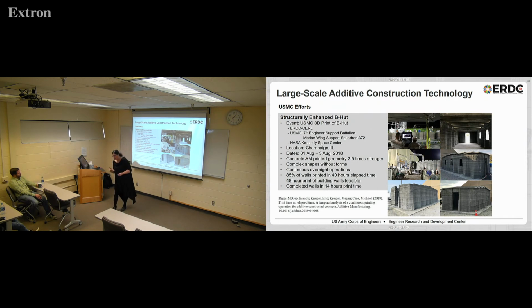And so if you feel about 6 layers down, it feels very firm. It feels like the concrete's already gone through some of its initial set. So we don't have to worry about how fast we can print, as long as we give enough time for the material to get that initial set. And we also don't have to worry about the cold joints.